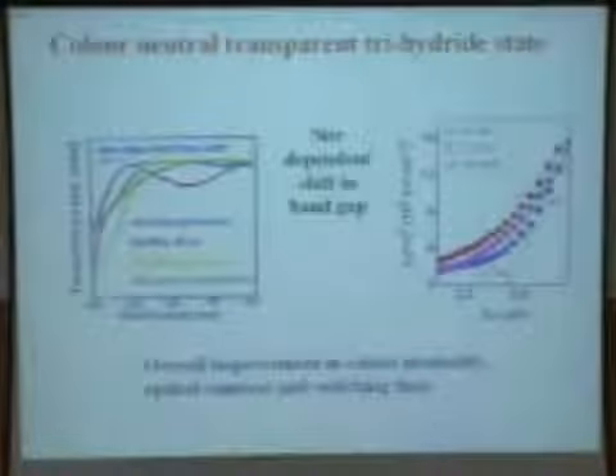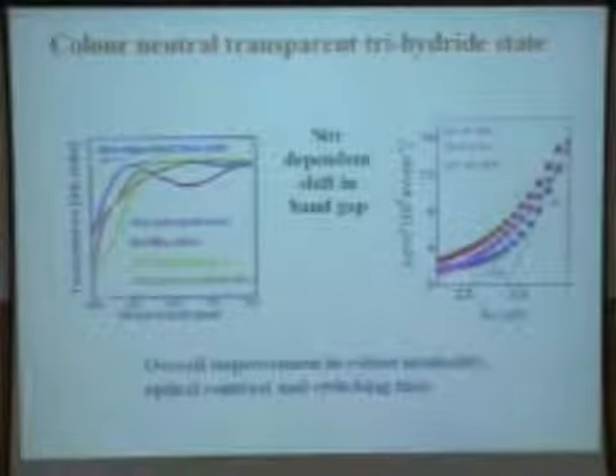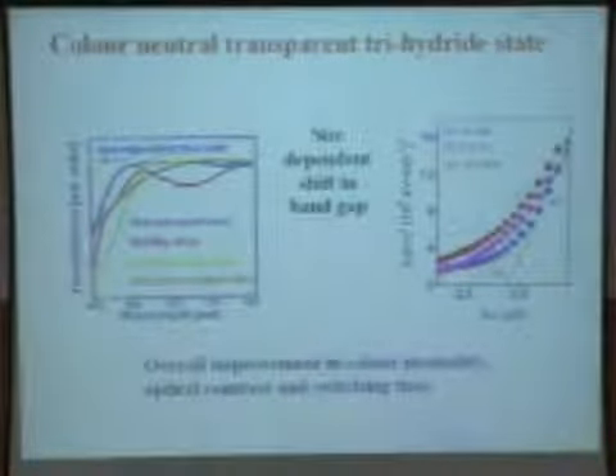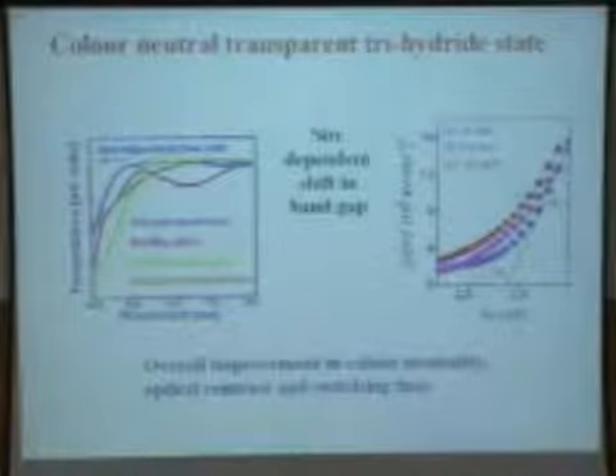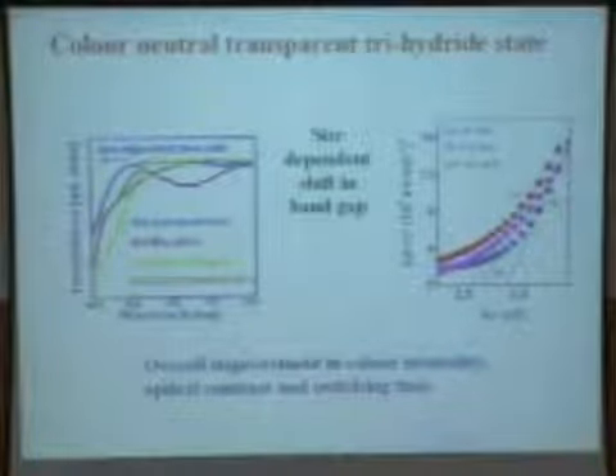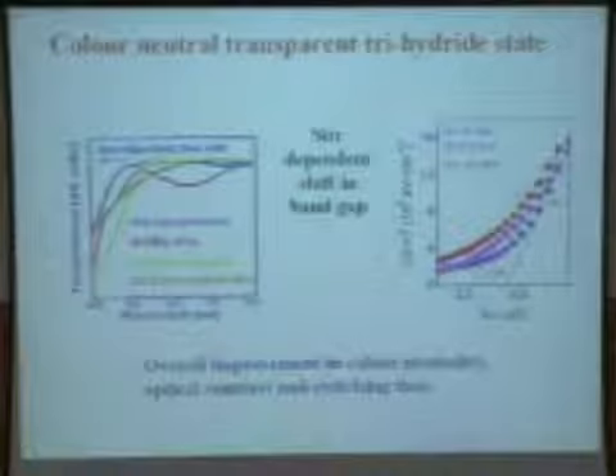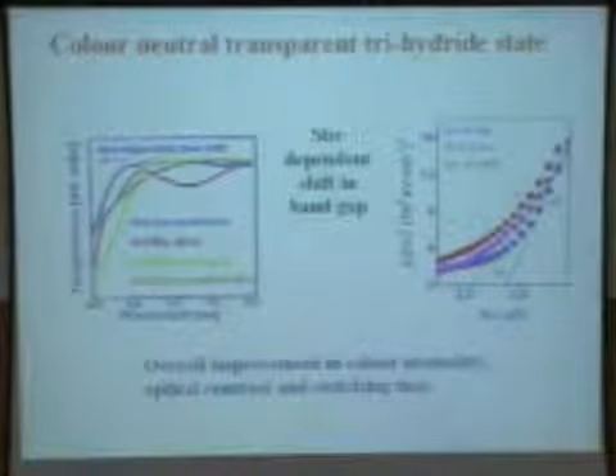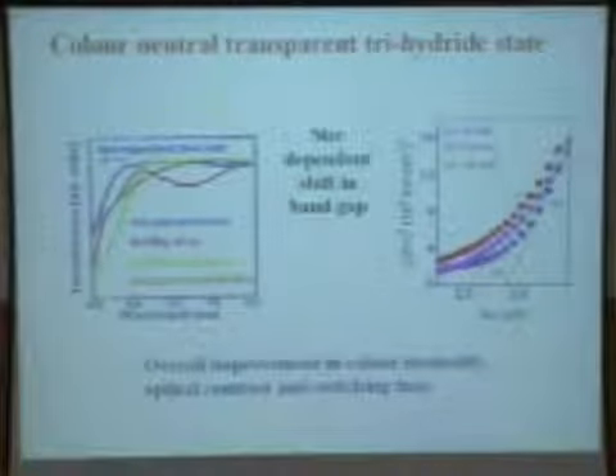Similarly, this is the color neutral transparent state compared for gadolinium nanoparticles, gadolinium magnesium alloys, multilayered, and polycrystalline. So there's an improvement in the color neutrality, and we can prove that that's actually due to the shift in the absorption edge of the nanoparticle trihydride state due to the reduction in the size.